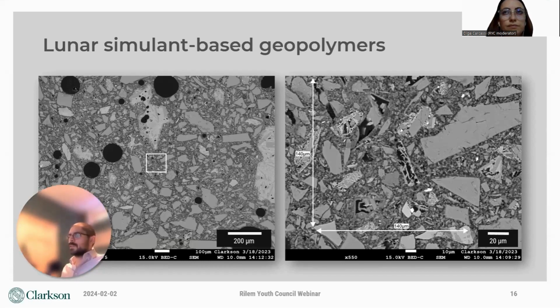But really what I want to focus on in this slide are all these air voids in the image on the left. We saw similar air voids in the mixed samples earlier, and we said the air voids would form stress concentrators and weaken the strength of the material. These air voids can happen due to reduced gravity like they did in the mixed samples, but they can also happen due to a variety of other effects.